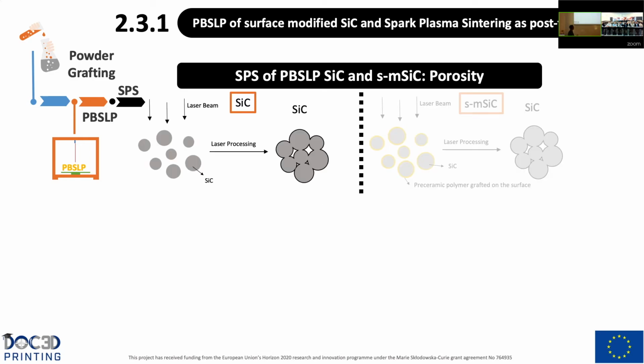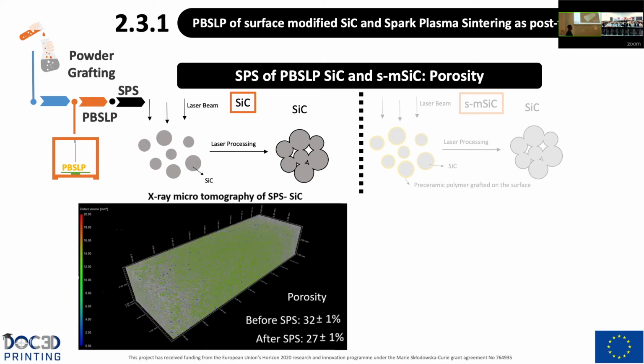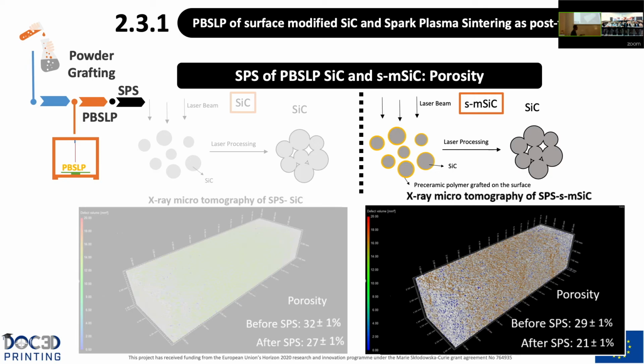Next point is to study the porosity after the post-treatment, again by using X-ray tomography. So actually here we are obtaining 27%. If we compare before spark plasma sintering, 32%. So we are decreasing the porosity by 5%. And regarding the surface modification, 21%. Remember before was 29%. So here we have a reduction in the porosity of 8%.